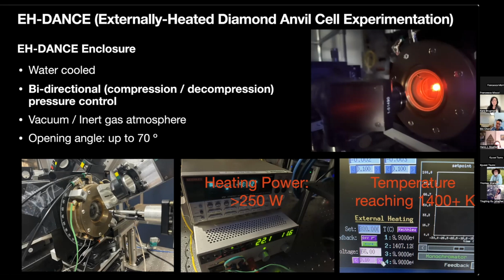We haven't done the FIB, the focused ion beam. It will be helpful to cut a thin section in the sample to see if we can find diamond there. But from our XRD data, it's pretty conclusive that we have powdered diamond forming.